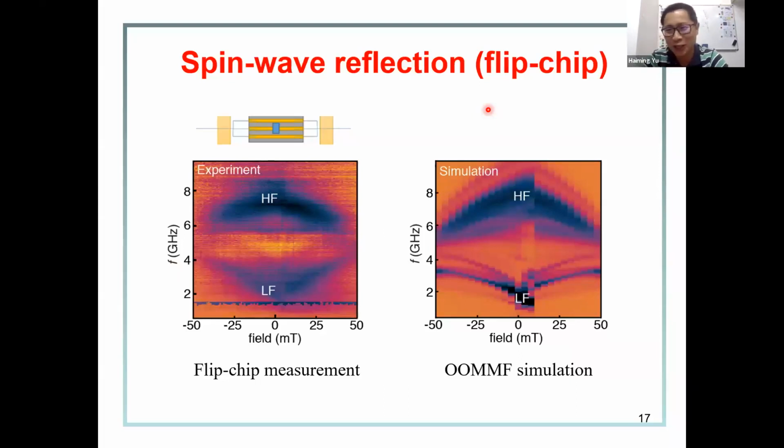Yes, it's a very good question. It is indeed a ferromagnetic material. If you consider the next neighbor spins on the atomic scale, it is a ferromagnetic exchange, that's for sure. The so-called exchange coupling between these two domains is a kind of effective exchange or effective coupling, not necessarily exchange. But I think the dipolar interaction definitely favors these two being antiparallel. Right. And for the dynamics, through the complex domain wall structure, which looks like a vortex in cross section, I don't know how this would contribute to the dynamics of these two domains. So it might need more investigation. Sure, thank you very much.